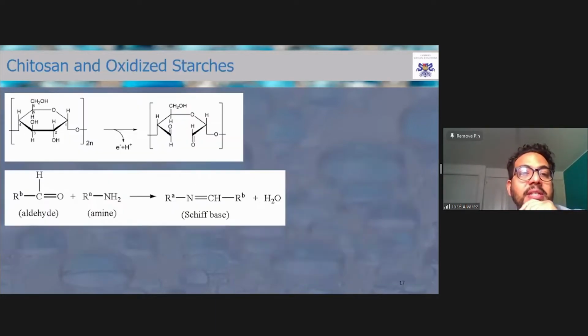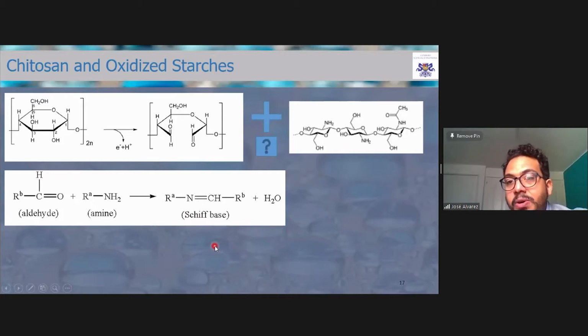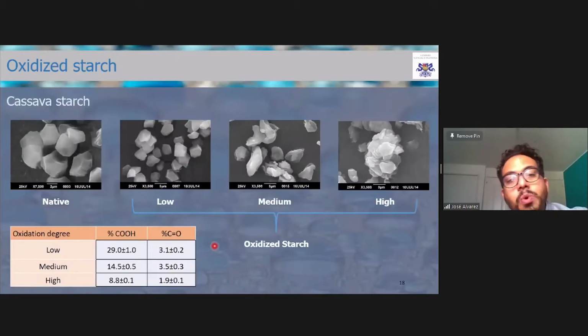So we decided to look at amylose and amylopectin structure, and we said, well, if we oxidize the structure, these primary alcohols will turn into carbonyl groups, and carbonyl groups from these amylose amylopectin modified molecules in starch, when they meet with amine groups from the chitosan, they could form a Schiff base. So ideally, if we put these two together, they would create cross-linking and we would be able to form hydrogels.